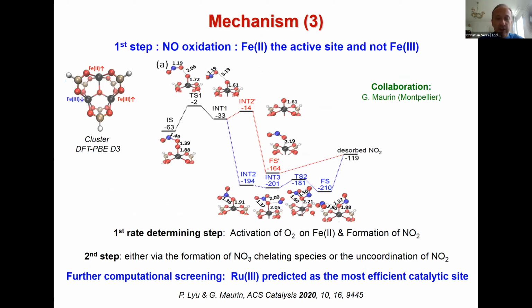First tentative calculation also has been done by Guillaume Maurin and his team in a recent publication in 2020, where they consider only the first step of oxidation. So the iron 2 is seen to be the most active site and not the iron 3, through the activation of oxygen. And then the second step here, there's a red and a blue path, considering either the formation of NO3 as a chelating species, or the uncoordination of NO2.